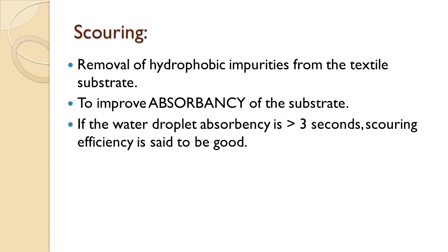So we need to remove these hydrophobic impurities so that hydrophilicity can be imparted to the substrate. By removing these hydrophobic impurities, basically we improve the absorbency of the substrate. It is said that generally by the water droplet method, if a water droplet is falling on the substrate and it gets absorbed within 3 seconds, then its absorbency is good.